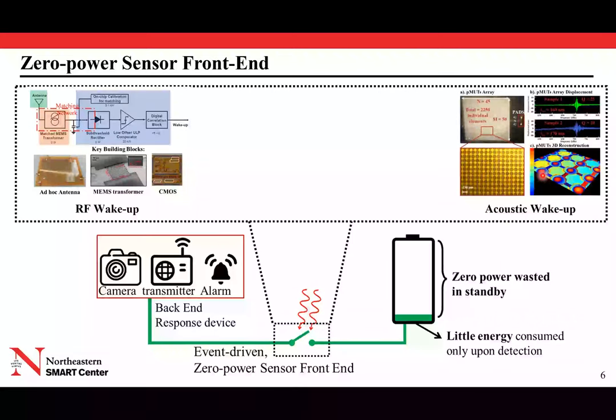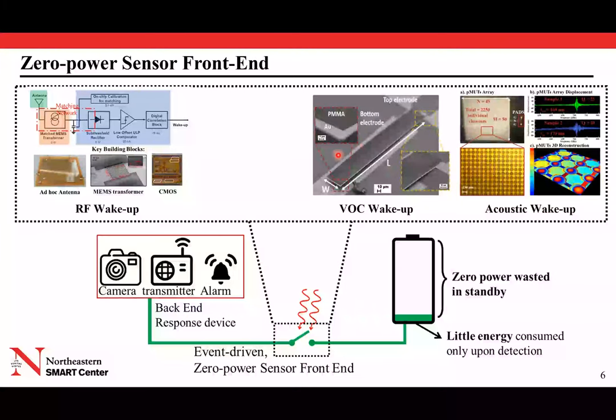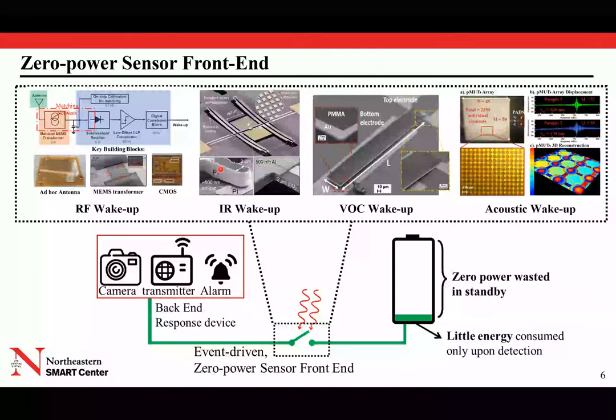So we use these piezoelectric micromachined ultrasonic transducers combined with MEMS switches to build acoustic wake-up receivers. We also build micro cantilevers that use a chemically sensitive layer. Basically, the cantilever would turn on and close a pair of contacts when it's exposed to a certain concentration of volatile organic chemical. And last but not least, we developed this infrared plasmonically enhanced switch, which is a micromechanical switch that turns on when it's exposed to a very specific wavelength of infrared radiation.